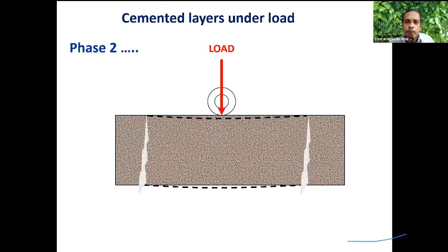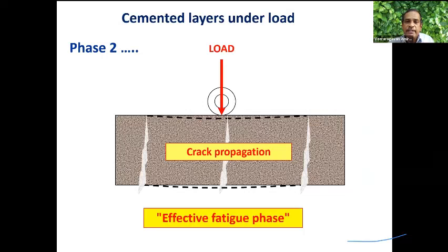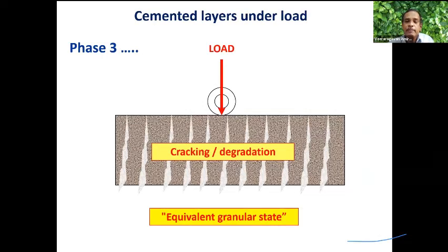Again, the crack will become more, the crack propagation phase or effective fatigue phase, and again, it will become an equivalent granular phase. Now, why I'm bringing this is that initially, when it was uncracked, it had some modulus value. With repeated application, it started developing cracking. And maybe at the end of 5 years, 8 years, 10 years, it will reach a stage of granular state. The modulus of the cementitious layer, which was 5,000 initially, will become 1,000 later. How do you consider that in the design? That is the challenge before you. How many years will it take for a pavement to reach a granular state in terms of modulus?